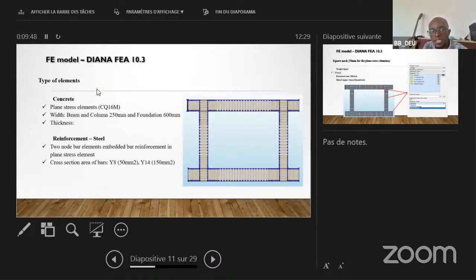So the type of element: we have two elements, concrete and steel reinforcement. For concrete, the concrete will be modeled, as mentioned in the DIANA manual, using plane stress elements, and the width for beam and column is 250 millimeters, and for foundation, 600 millimeters. For reinforcement, we take two-node bar elements embedded in the plane stress element. And the cross-section area of the bars is Y8, which corresponds to 50 square millimeters, and Y14, which corresponds to 150 square millimeters. Here we can see in this picture.